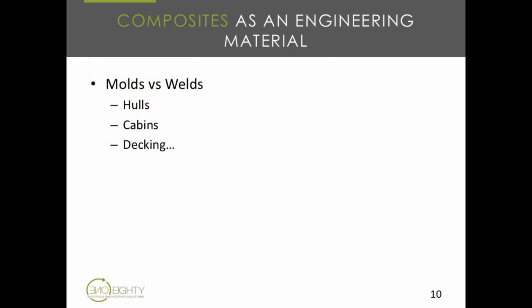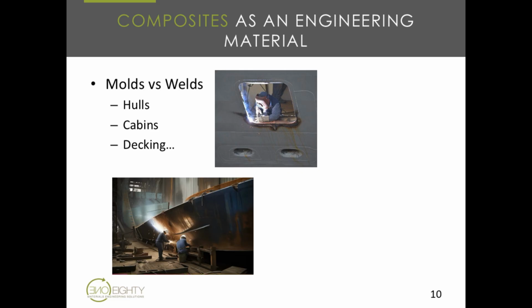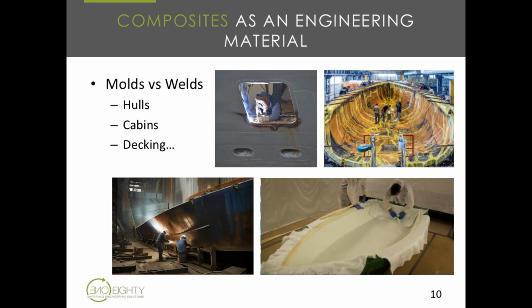Okay, so in terms of how composites are used in manufacturing versus how metals are worked with, especially in terms of boats: metals are typically welded. They are taken from plates, as can be seen below, and any sort of fittings, at the top there you can see a window fitting being manufactured, or welded, actually. So it's very strong, yes, but it is labor intensive and it does pose a high risk, because if the weld is not done correctly, if the procedure isn't qualified, you're at risk of failure. Whereas with composites, you are able to build an entire vessel in one go if you have the correct mold. So you'll use a wooden frame and design a mold of the vessel that you'd like to make, if it's a yacht or a larger vessel. And that mold will be set up so that you can lay down, in this case, glass fiber laminates.